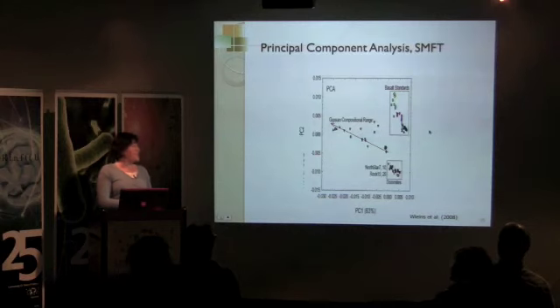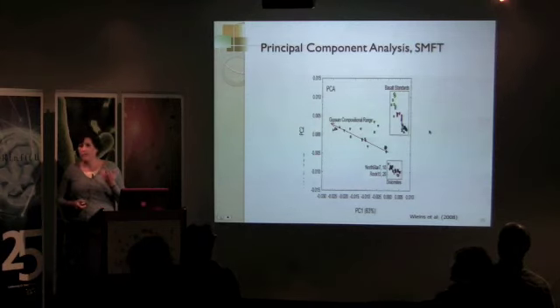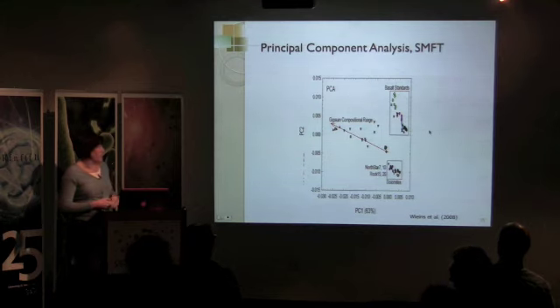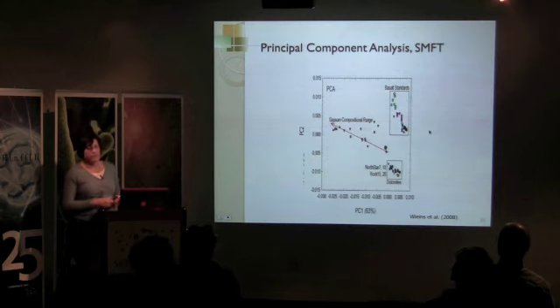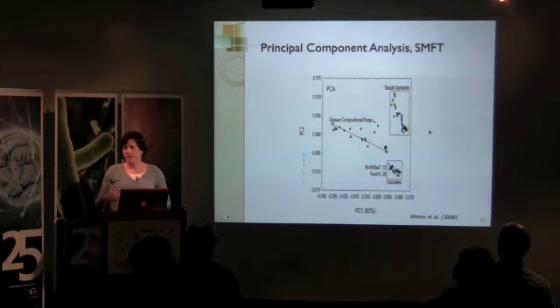And in fact, ChemCam turned out to be a real star in this exercise because of the rapid turnaround and because of the ability to process the data so quickly. Here's again a PCA analysis for the SMFT for one of the samples, and again we're able to show we can distinguish between dolomites, basalts, and a range in gypsum compositions. So again, ChemCam showed its value as the scout instrument.